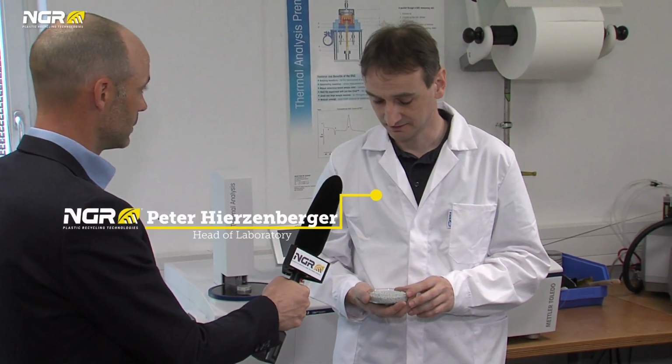Yes, David, I can confirm this number. That is one sample of the pellets, and in the lab we measured several of them and reached an average value of 0.80, which coincides perfectly with the online IV measurement.